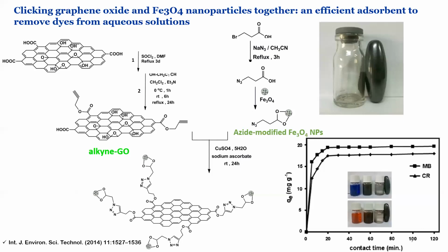And what I talked about previously, magnetic nanoparticles were attached physically. It was a non-covalent attachment onto the sheets. I decided to see how I can attach nanoparticles chemically onto the graphene sheets. So I modified the nanoparticles with azide, put the alkyne on the sheets, and then clicked them together. And here's what we got.